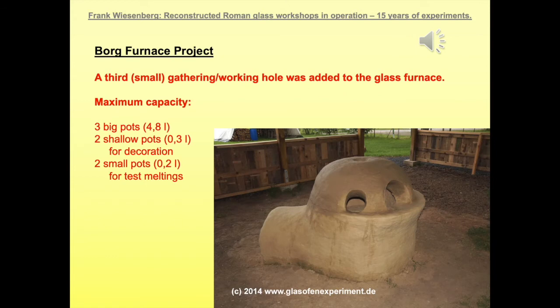The addition of the third small gathering hole added a small space for melting experiments to the capacity of the large glass furnace at Borg. So 3 big pots, which are up to 4.8 liters each, 2 shallow pots for decoration, 2 small pots for test meltings can be inserted simultaneously inside the glass furnace.